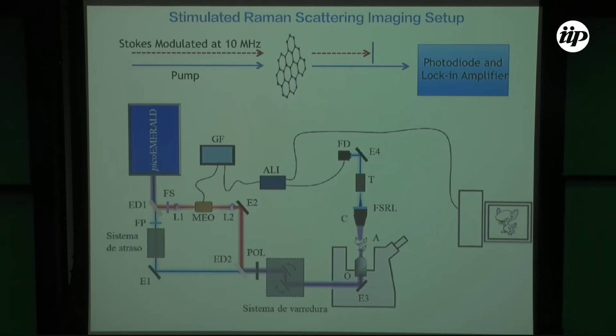So what we do is we modulate one of the laser beams. In this case, we modulate the Stokes beam with a high-frequency modulator, about 10 megahertz. It goes to the sample, and then we block this laser after it goes through the sample, and only detect the pump beam. And then we detect the pump beam with a photodiode that is connected to a lock-in amplifier that only reads the frequency of 10 megahertz, okay? It means that when there is some vibrational mode in your sample that matches the energy difference between this laser and this one, there is some energy transfer from this laser to this one, and it's modulated at 10 megahertz. Okay, and then I can detect this with a lock-in amplifier. Okay, so that's the full system here.